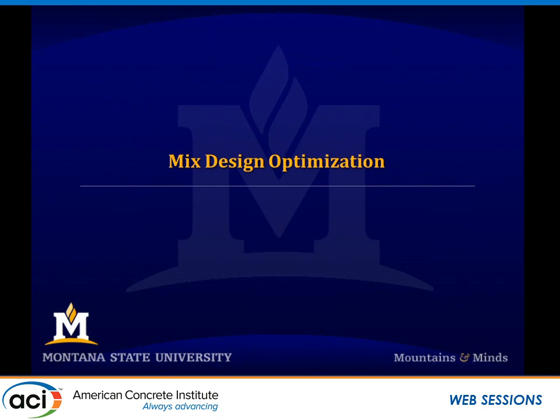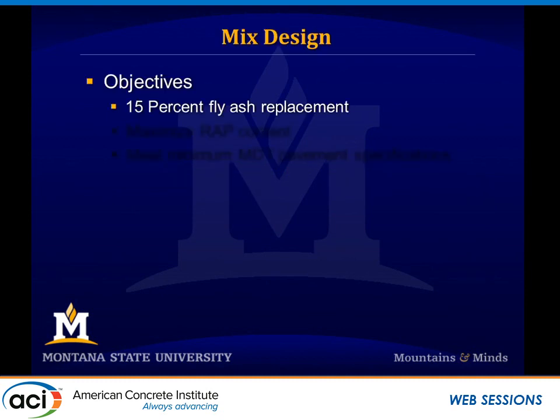All right. So once we had the RAP source, in terms of the mix design optimization, well, how do we come up with mix designs to meet our objectives? Our objectives were we wanted to use 15% fly ash replacement. We wanted this to help control ASR, and this to help with just on the green side of things. We just wanted to replace some of the Portland cement. So we had that fixed parameter, 15% fly ash replacement.